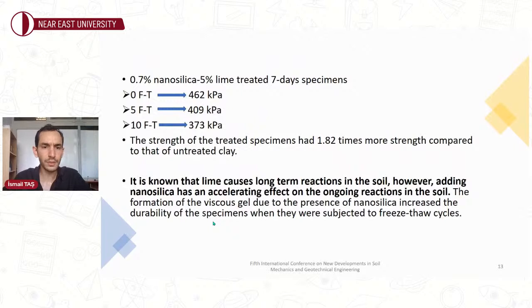An evaluation of the strength decrement of 7-day, 0.7% nanosilica and 5% lime treated specimens shows that at the end of 5 freeze-thaw cycles, the strength of the specimens was 409 kilopascals. After 10 freeze-thaw cycles, the strength of the specimens decreased to 373 kilopascals.